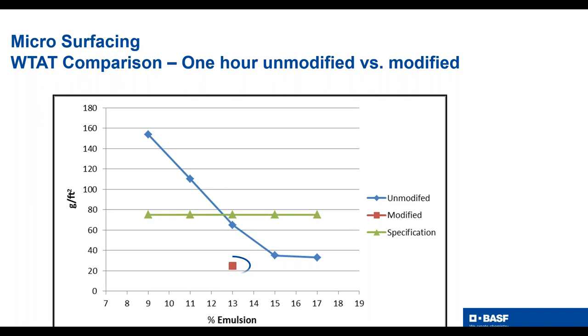And what I want to get at here is, if you're using the polymers, you have to be very careful for some of the tests, that you let the polymer really do the work that it's intended to do. And you don't want to take asphalt out of some of these microsurfacing systems and cause the polymer to help benefit your test, because just like this graph, it will for sure benefit the 1 hour and 6 day soaks. But make sure that you have the right emulsion content in there for the microsurfacing mixes.